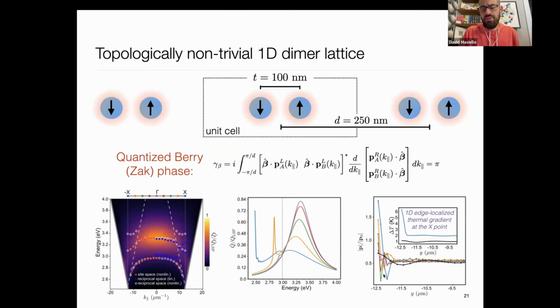And interestingly, I'll have you focus down here on the bottom plot. What we found is that in a 1D Bravais lattice, like you see here, maybe just focus on this blue curve here, that we actually calculated the temperature rise, and we're zoomed in here just on the far left edge of a finite lattice that I think was 80 microns in length. And this was really shocking to us, that the temperature rise grew in right at the edge of the lattice and fell back, and not quite to room temperature. There's a reason for that I can explain later if you're interested. But there is a stark contrast in the thermal gradient being basically homogeneous and very low, the temperature being quite low in the bulk region of the lattice, and then rises up on the edge.